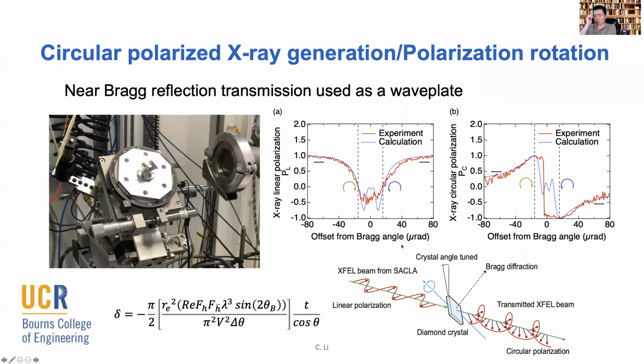But it turns out it's difficult to do. The reason is we do not have an easy approach to create a wave plate for hard X-rays. The X-ray we are using is at 24 keV, which is not easily tuned for polarization. Then we went back through the literature to see how people did it. It turns out for free electron lasers, people use a diamond crystal mounted very close to its Bragg condition, and then slightly offset from the Bragg condition to tune the polarization of the hard X-rays. This can be done because the diamond basically works like a wave plate, with the Bragg diffraction having to happen 45 degrees off the plane that the beam was in.